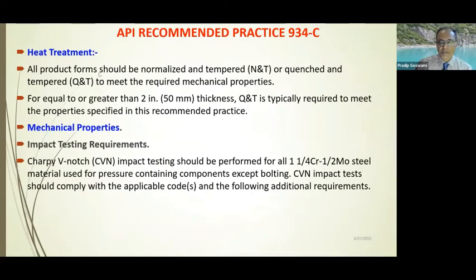Now, heat treatment, generally all products, these steels are either normalized and tempered or quenched and tempered. And when the quenched and tempered steels are used, the QT requirement is very specific. And generally speaking, when somebody is handling QT steels, one has to be very careful in fulfilling the requirements at every stage of fabrication.